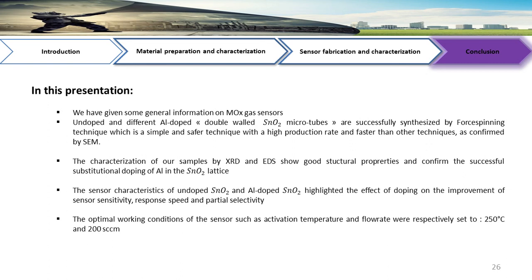The sensor characteristics of undoped tin oxide and aluminum doped tin oxide highlighted the effect of doping on the improvement of sensor sensitivity, response speed, and partial selectivity. The optimal working conditions of the sensor, such as activation temperature and flow rate, were respectively set to 250 degrees and 200 SCCM.